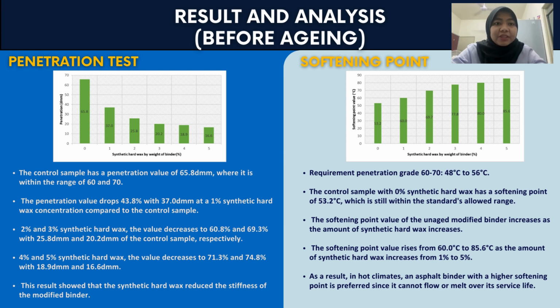The penetration test is conducted to find asphalt binder stiffness or consistency. The lower the penetration result, the more stiff the binder. The control sample has a penetration value of 65.8 dmm, which is within the range of 60-70. When synthetic hard wax is added to the asphalt binder, the penetration value decreased and did not achieve the range. This result showed that synthetic hard wax changed the stiffness of the modified asphalt binder.